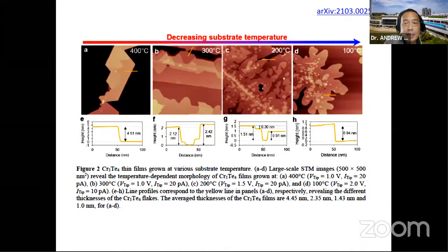This is the STM data showing growth at different temperatures, and even at 100 degrees centigrade, which is a very low growth temperature and certainly compatible with silicon CMOS technology, you can see we can grow this monolayer chromium telluride film. You can see this is the step height. That's about one monolayer, okay, 0.9 nanometers.